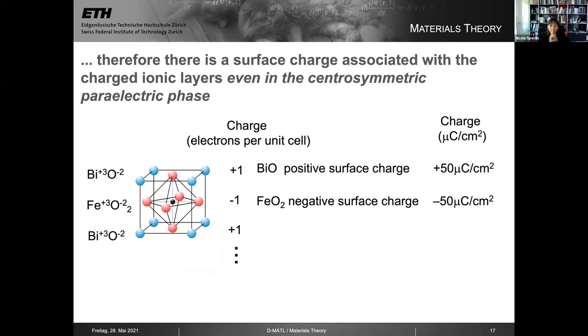As a result of this, because my bismuth ferrite in its centrosymmetric phase doesn't have zero as an allowed value of its polarization, this means that there is a surface charge associated with the polarization even in the centrosymmetric paraelectric phase. And maybe it's even more conceptual to think of it in this cartoon way. This layer which contains bismuth and oxygen is a positively charged layer. And so if I put a surface above that, I'm going to have a positive surface charge. This has nothing to do with any ferroelectric polarization. It's because of the internal layers of the material. Likewise, if I make the surface just above the FeO2 layer, I'm going to have a negative surface charge associated with putting the surface just there.